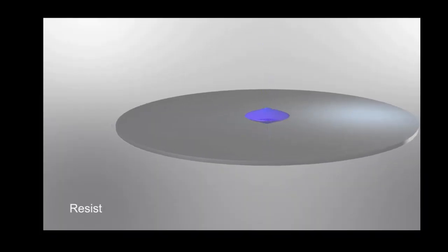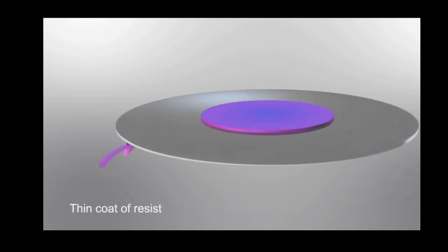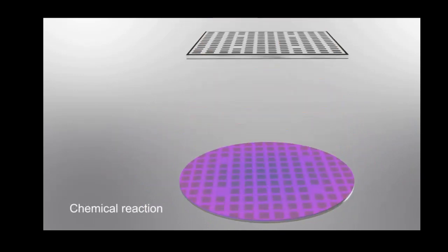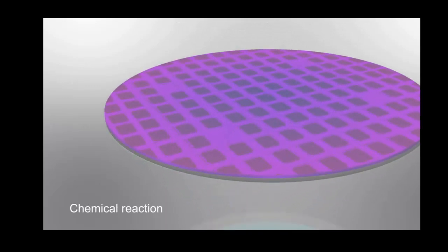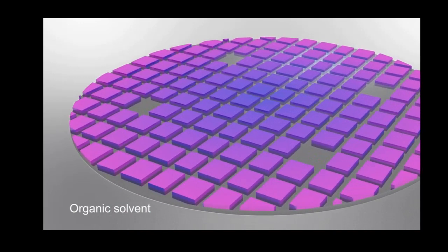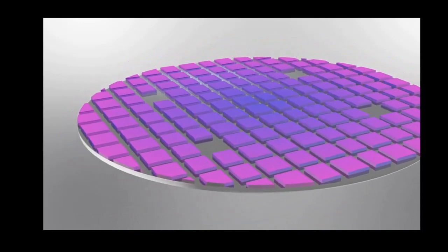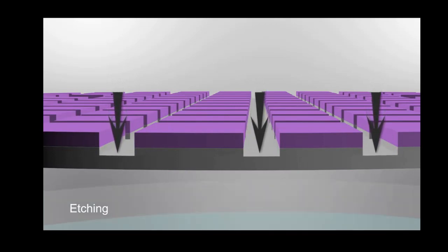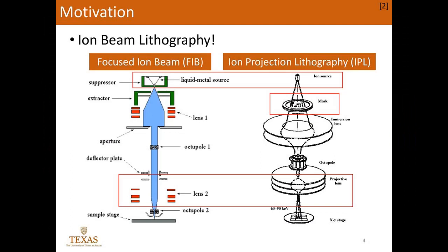A pattern mask is applied onto the substrate coated with photoresist. This mask blocks the light, so only the unmasked region of the material will be exposed to light. A solvent called the developer is applied after exposure. In a positive photoresist, the exposed photosensitive material gets degraded by light, and the developer washes away the exposed regions, leaving behind a coating where the mask was placed. In a negative photoresist, the material is strengthened, either polymerized or cross-linked by light, and the developer dissolves away only the regions not exposed to light, leaving behind a coating in areas where the mask was not present.